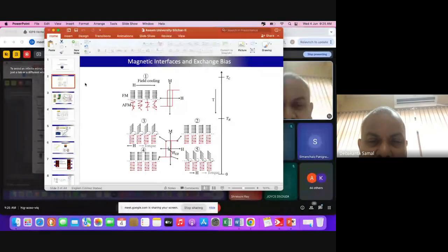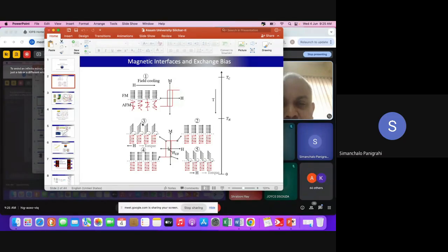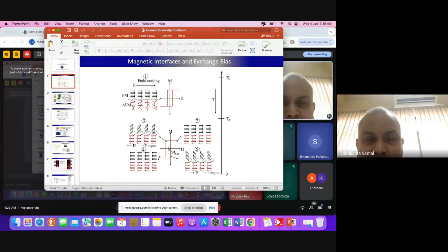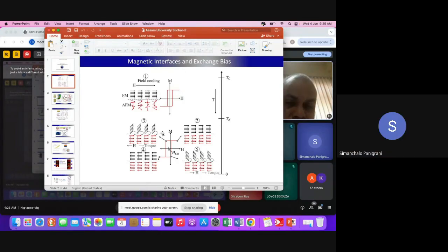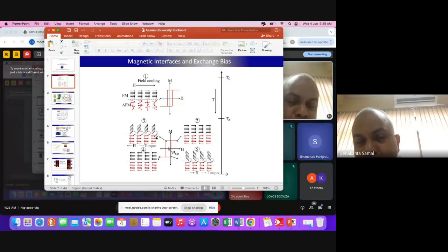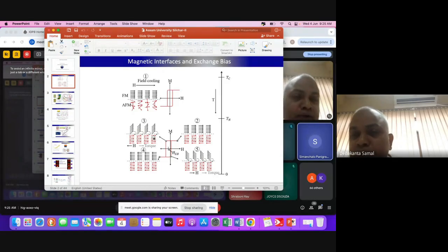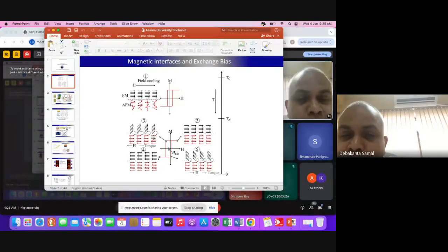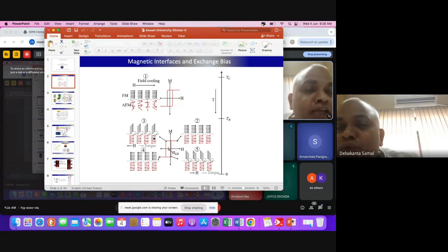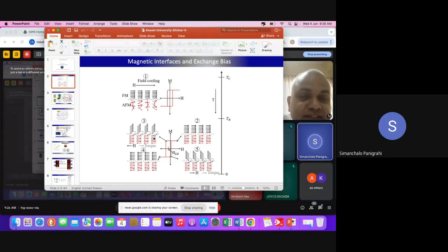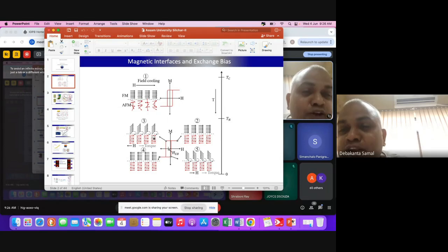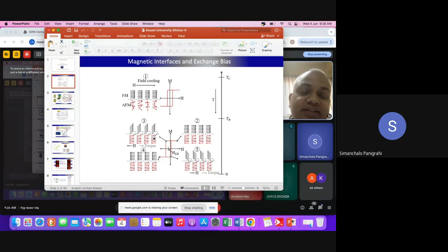There is already an antiferromagnet. If you look at the three, there is already, you see, the ferromagnets were all aligned along the positive x direction, let's say. But there is the antiferromagnetic coupling between this. To break the antiferromagnetic coupling between two spins, it costs you more energy. So what it will do, it will slowly rotate the ferromagnet, but somehow there is a glue. This antiferromagnet coupling is not allowing it to go freely to the second quadrant. So you really require more field to flip that chunk of ferromagnet spins into the second quadrant. Okay, sir. Got it. Thank you.